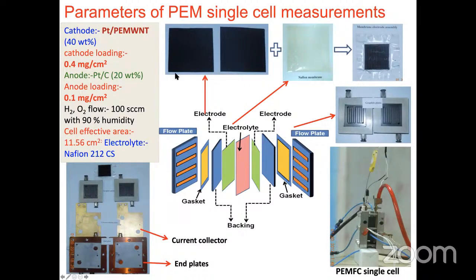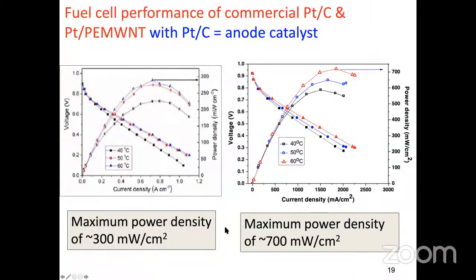So this is your anode catalyst, okay, and this is your cathode. And these are the electrodes. In between you will keep the Nafion membrane, that is a proton conducting membrane. So make the membrane electrode assembly, and then allow the hydrogen gas through the anode side and the oxygen from the cathode side. So you have the graphite plates, and make the single cell, okay, single cell. So all the components are given here: graphite plates, MEA, and then current collectors, and the end plates. So once you have done that, then we'll check the performance.